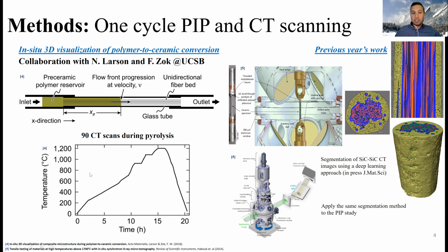And within this, she took 90 CT scans equally spaced within those 20 hours. And she used this rig here, but not for mechanical testing, but rather for just providing the heating for this sample while being able to CT scan it.